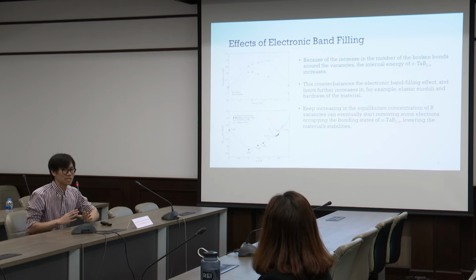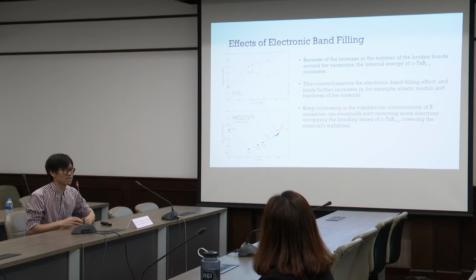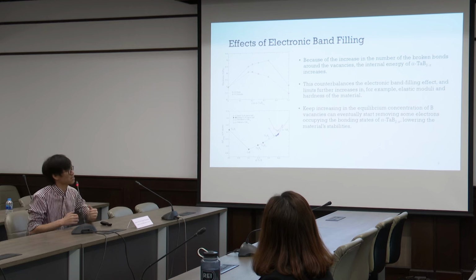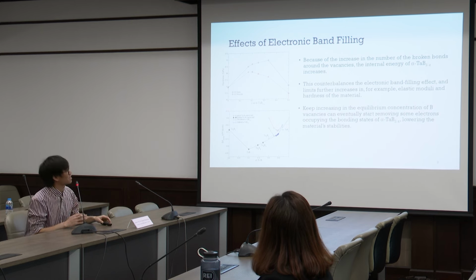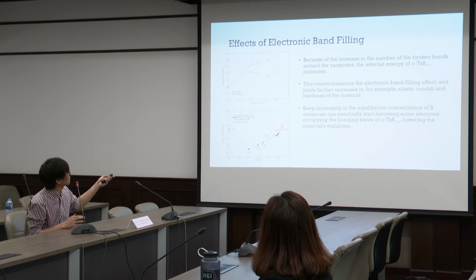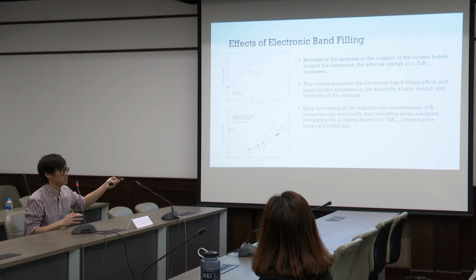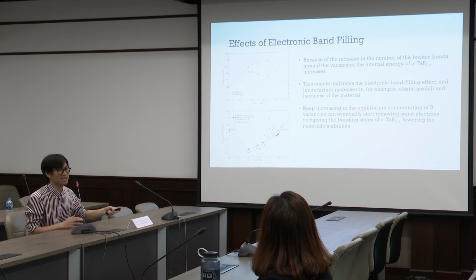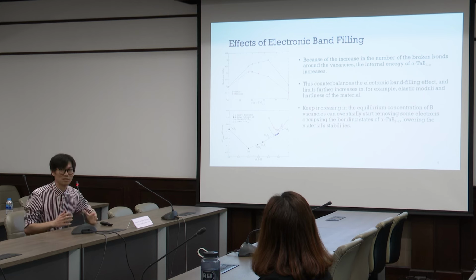One thing that we have to be careful about is that when the concentration of vacancy increases, you basically have more broken bonds in this compound, and that results in an increase in the internal energy of the system. This counterbalances the electronic band filling effect I mentioned before, and it limits the further increase in, for instance, the hardness. As you can see, the hardness increases up to this point where x is about 0.33. If you further increase the concentration of vacancy, the hardness drastically drops, because you create too many broken bonds in the system.